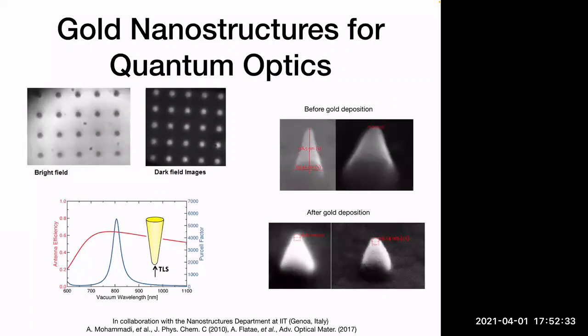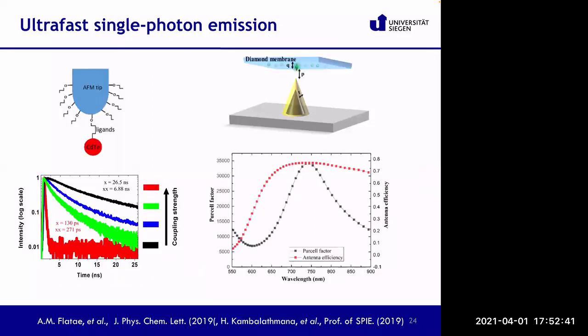And theoretically, you can get Purcell enhancement that are really more than 3 orders of magnitude. And we applied that to quantum dots, and we showed that we can have a change of the spontaneous emission rate by more than 3 orders of magnitude. This is shown here in these lifetime curves, where you essentially look at the exciton and bi-exciton recombination rate of a cadmium telluride quantum dot placed on an AFM tip. So the AFM tip is going close to the nanocone, and then when the coupling is strong, you get this very strong emission rate. But what we want to do is to really apply this to diamond color centers.